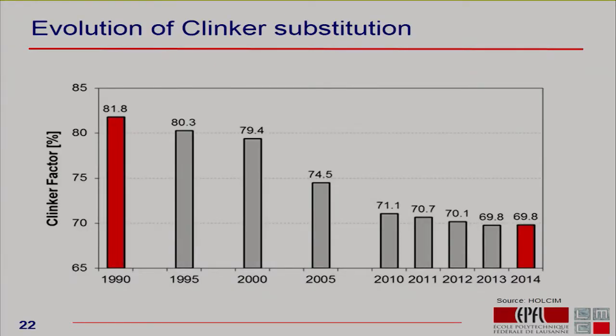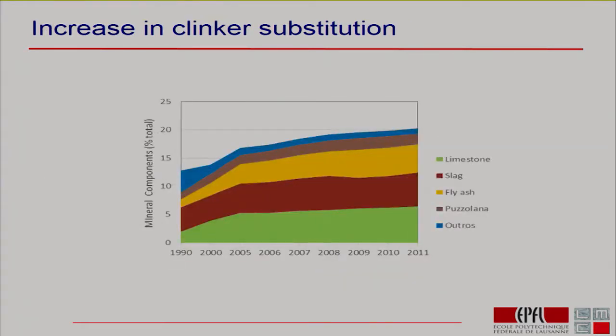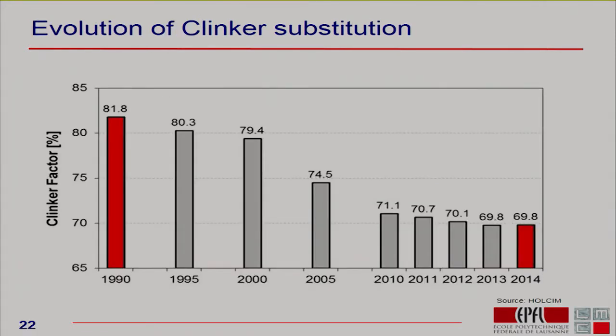And if we take the figures for Holcim, which is one of the biggest international cement companies, these are the worldwide figures for their factories. You can see over the past few decades, the average amount of clinker they have in their cement has been reduced by more than 10%, and this reduction of more than 10% is equivalent to a more than 10% reduction per ton in CO2. So that's great, but what we actually see is that this strategy for replacing cement with other things is kind of leveling off. You can see that here from the figures from Holcim.